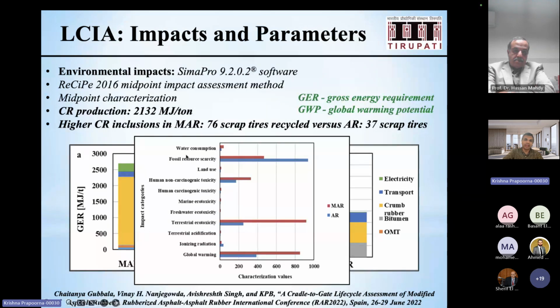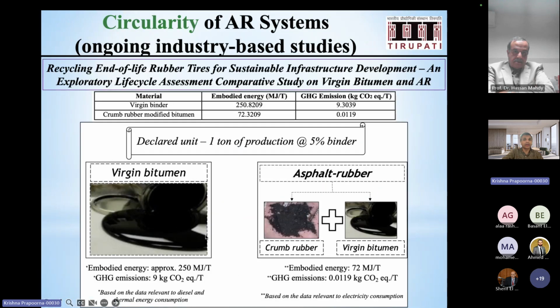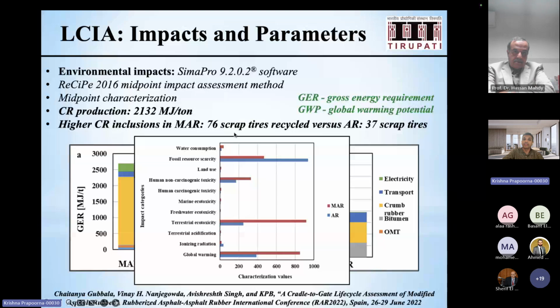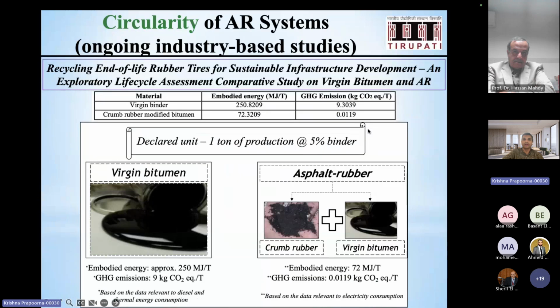Okay, so you're looking at the impact categories. There are 18 different types of categories. One is water consumption, resource scarcity, land use, carcinogenic toxicity, and then leachate potential, global warming. Basically, MAR functions much better than asphalt rubber in terms of resource scarcity, because you're using industrial waste, so that's a win-win situation. And it also functions very well in terms of radiation that you see here, and also acidification. So you're looking at 76 scrap tires being recycled in MAR, modified asphalt rubber, versus 37. So it's double now that we can use recyclability there.